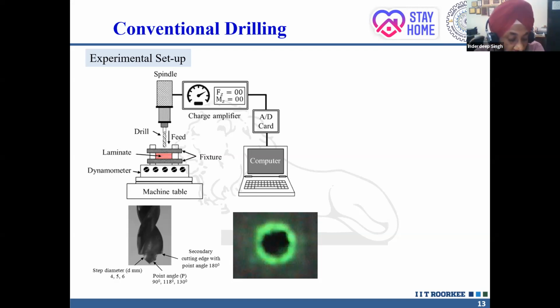So that is the kind of equipment and machines which are being developed, because if you are able to dynamically control the feed rate, initially the feed rate can be slightly higher, but as soon as the drill is reaching towards the lowermost laminae or lowermost plies or lowermost layers of the composite material, in that case the feed rate is reduced. Why? Because of the feedback control mechanism. So if we use that kind of mechanism, automatically we will be able to mitigate or reduce the damage that is being observed around the hole.